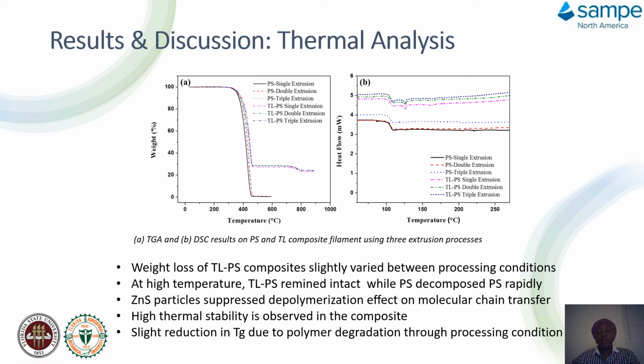It also shows that there is a slight reduction in the glass transition of the polymer. This is due to the degradation through the processing condition, as the material was being processed 3 times.